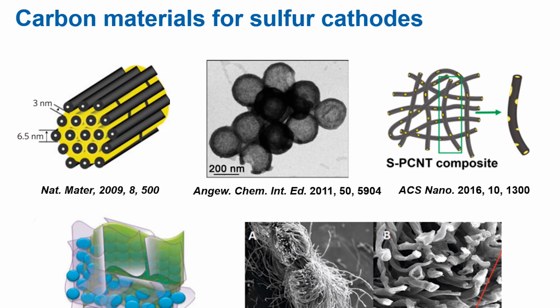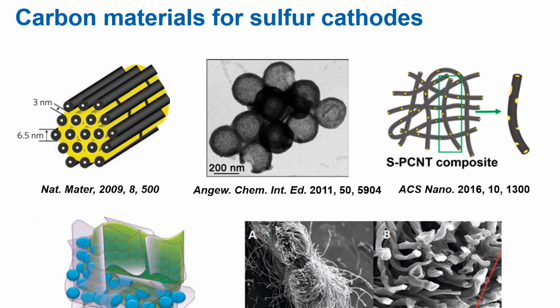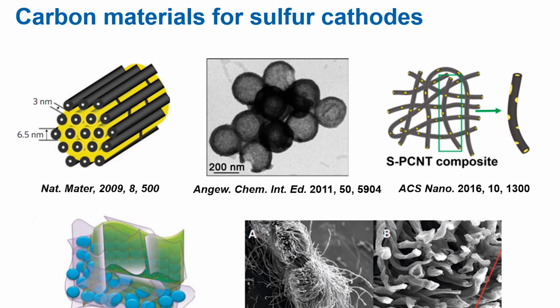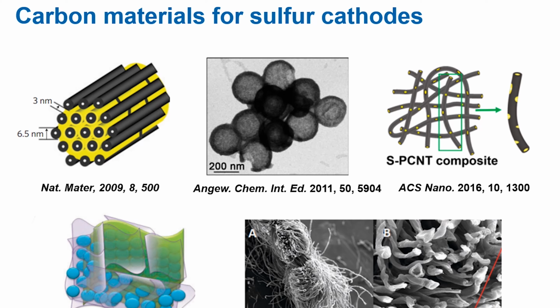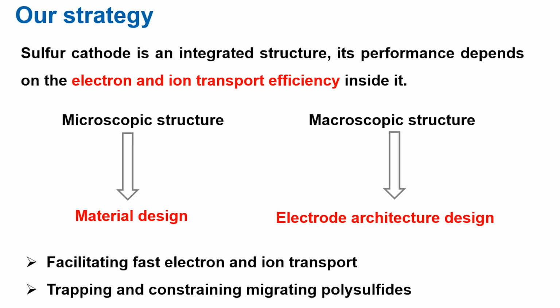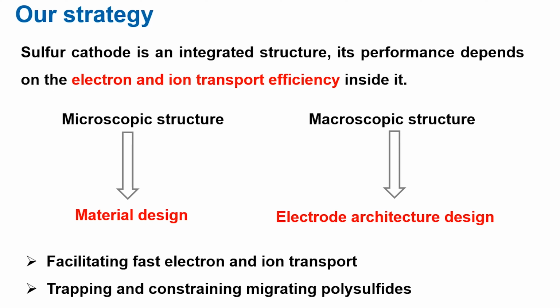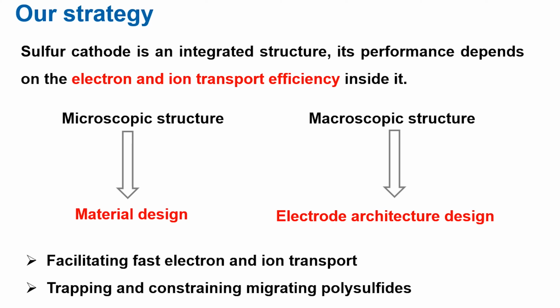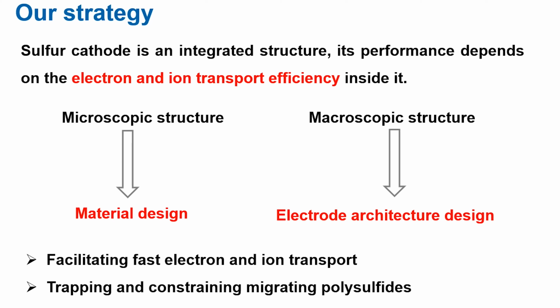To address the above problems and challenges, carbon materials have been widely used for the construction of sulfur cathodes because of their advantages of high conductivity, high porosity, and lightweight. In our strategy, we realized that the sulfur cathode is an integrated structure, and its performance depends on the electron and ion transport efficiency inside it.